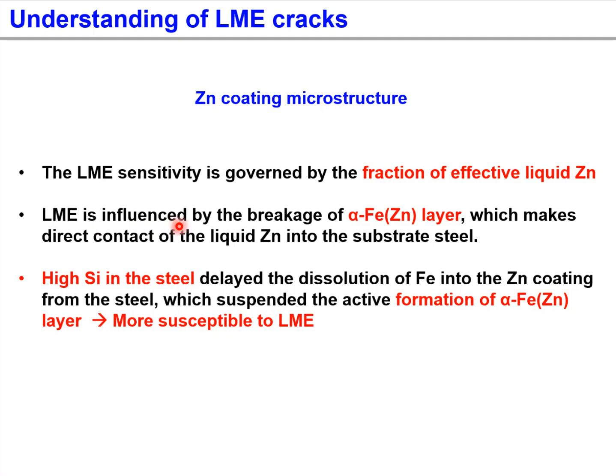LME is influenced by the breakage of the alpha Fe zinc layer, which makes direct contact of the liquid zinc with the substrate steel. High silicon in the steel delayed the dissolution of iron from the steel into the zinc coating, which suspended the active formation of the alpha Fe zinc layer, making it more susceptible to LME cracks. So the fraction of liquid zinc and the alpha Fe zinc layer are the key factors from the zinc coating side.